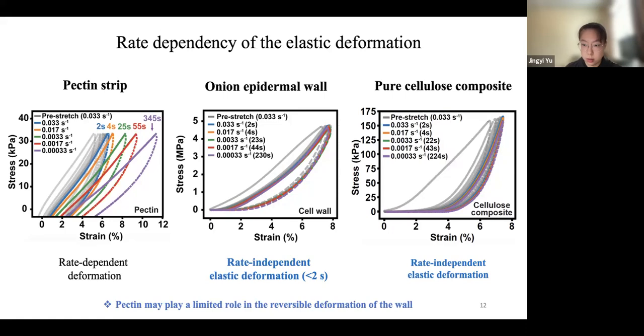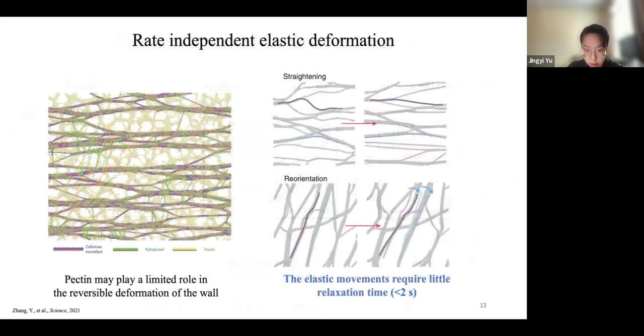So by comparing the cell wall material with a pectin and cellulose composite, it's overall suggesting that the onion epidermal wall behaves more like an elastic cellulose network rather than a viscous pectin gel reinforced with cellulose. And this test also allows some interpretation in terms of the molecular movements underlying this rate dependency.